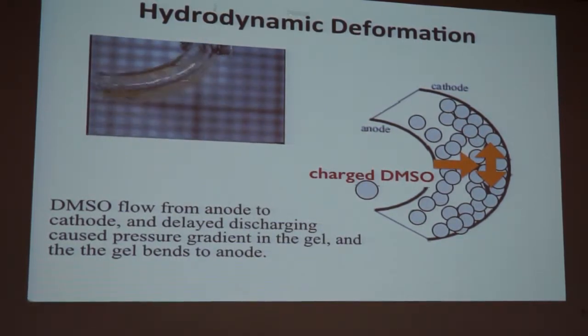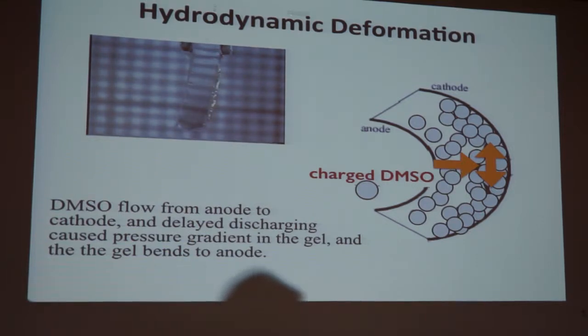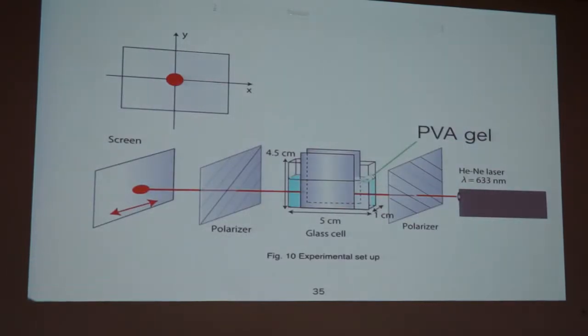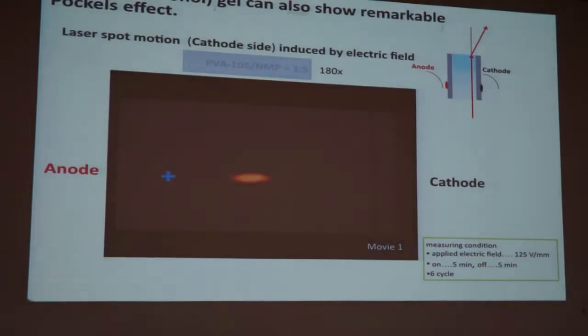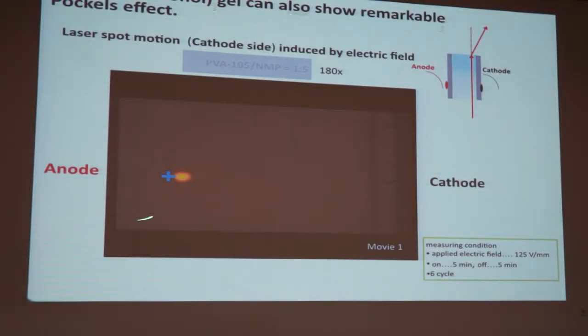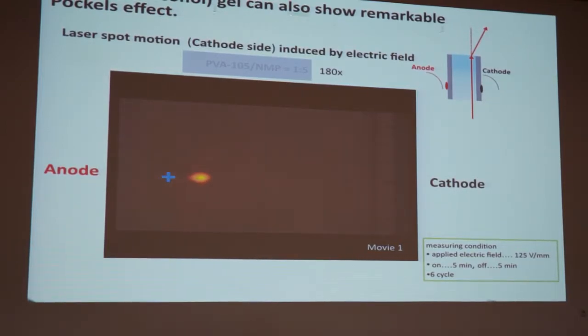The mechanism is simple. A charge injection from, in this case, the anode, can lead to that kind of function. But we employ that kind of gel for electro-optical function. This is the case. Very clear and clean diffraction, very good performance. In this case, we can use this material for a very long time because we prepare the gel in a dry vessel.